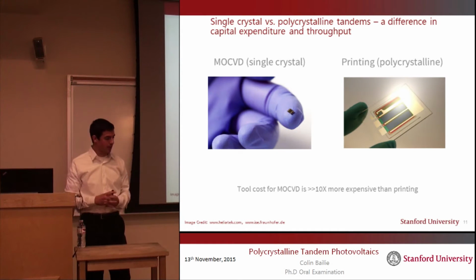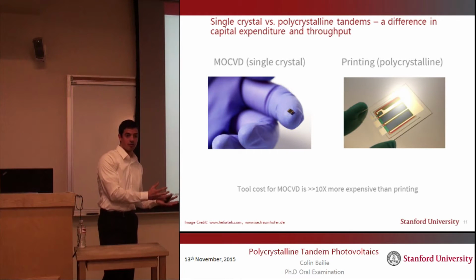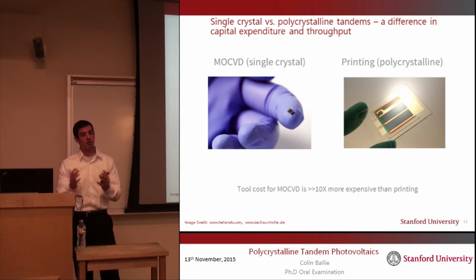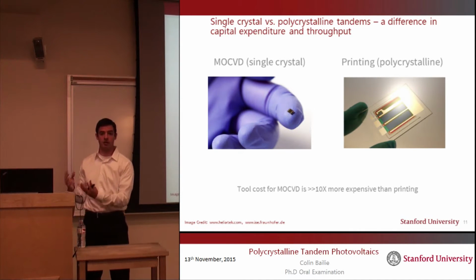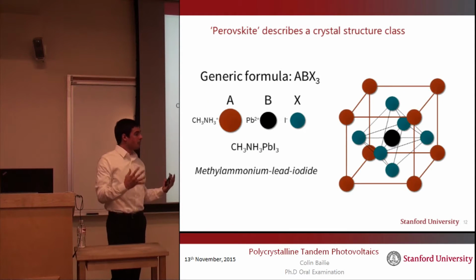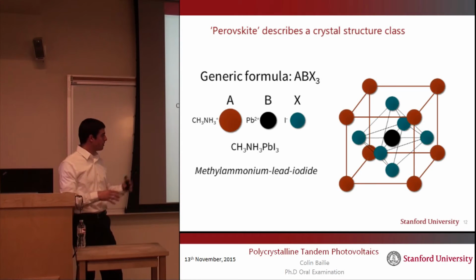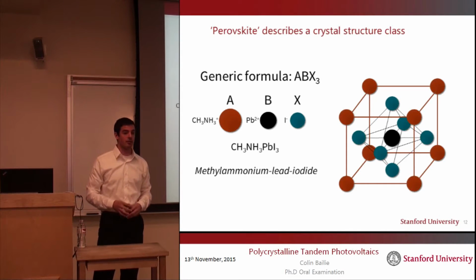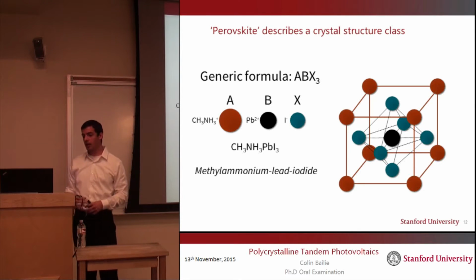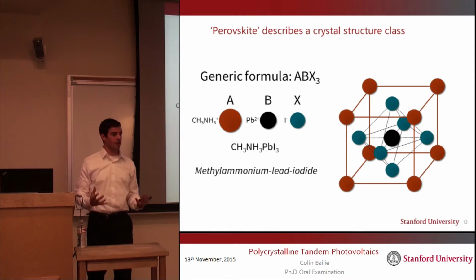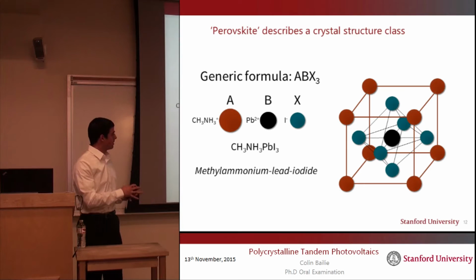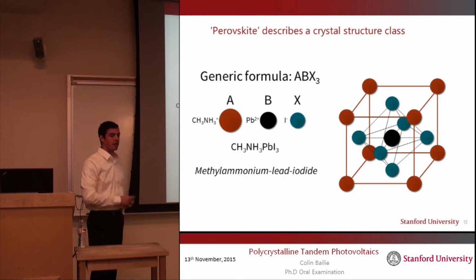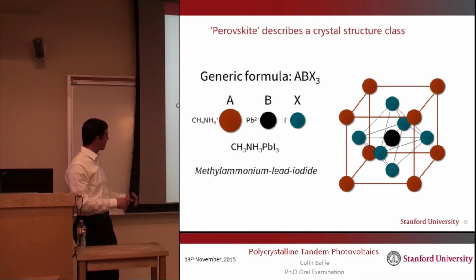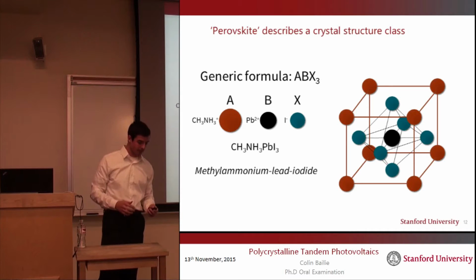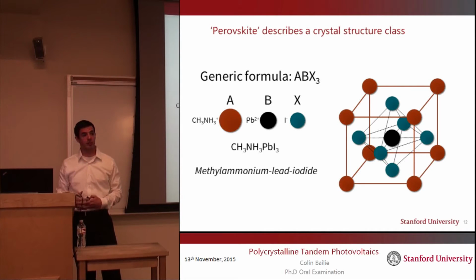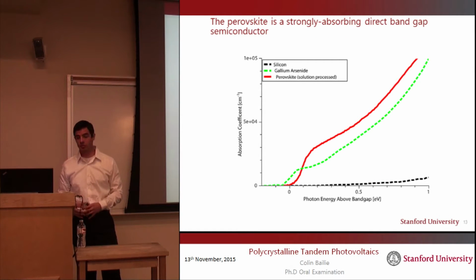So our two options on the table right now are either to make something that is incredibly efficient, which is what we want, but is prohibitively expensive to make, or something that has the cost structure that we like, but is prohibitively low in efficiency. And now there's something that potentially bridges that gap. A few years ago, simultaneously out of both Oxford and EPFL, researchers figured out a way to use a material called a metal halide perovskite in solid-state solar cells. This metal halide perovskite that they chose to use used lead as the metal, iodine as the halide, and an organic called methylammonium that served as a spacer in the lattice. And this material, this methylammonium lead iodide, ended up having a lot of advantageous properties for solar cells.